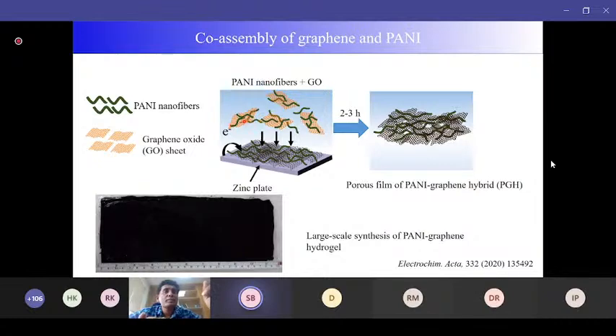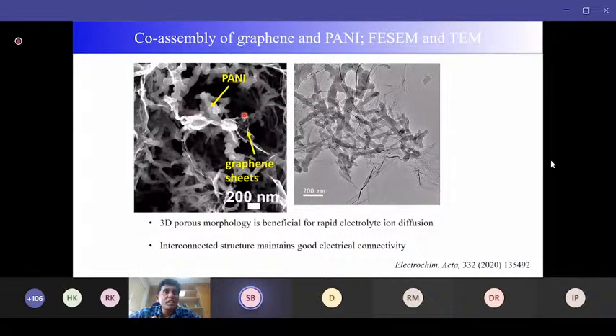So they remain associated with the graphene, and then they assemble exactly the same way as I discussed. They assemble in the form of a hybrid hydrogel. This process is known as the co-assembly of graphene and polyaniline, known as PANI. So we got a bigger hydrogel structure, and from the FESEM image, as you can see, these thinner sheets, the graphene sheets, wrap the polyaniline nanowires, and there are still a lot of pores available. Through these pores, the ions can go inside the material so that its individual surfaces can be accessed, and you can expect very high areal performance. And from the TEM image, you can also see that these thinner sheets are graphene sheets, and these nanowire structures are polyaniline.